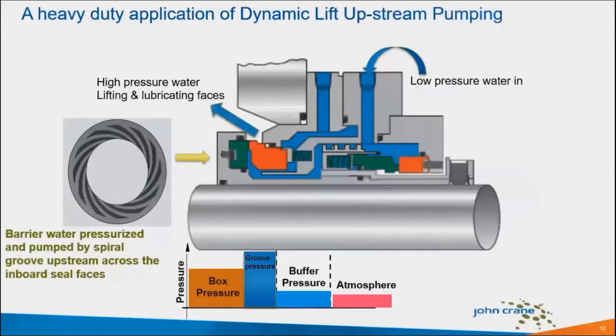And the preferred arrangement of this spiral groove technology in a slurry seal presents the spiral grooves on the inboard side of the seal, and on the outboard side of the seal, we can see a conventional contacting seal running in water, low pressure water, probably 20 psi water. So its sealing challenges are very, very minimal, and it has a pumping ring on the OD of it, so it forces some of that barrier water down under the ID, the inside diameter of the inboard seal. So that red face on the inboard side is running against a green face, and the green face is representing the mating ring, and that's the part with the spiral grooves on it.